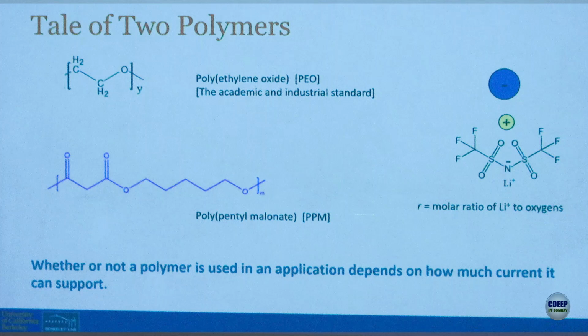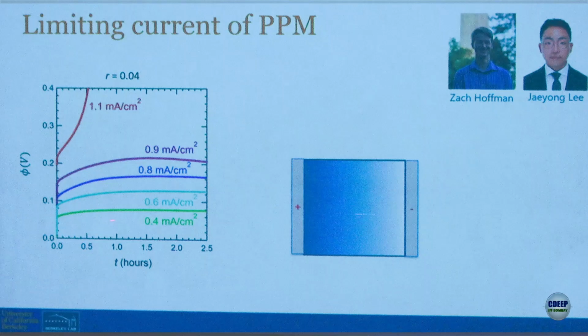And whether or not I can use this polymer in the application depends on how much current it can support. So the question is, how do you measure that current? Well, in this symmetric cell, it's very easy. You apply a current, and the voltage goes up and saturates, and then you see some funny business at 0.9, which you will ignore. And then at 1.1, the voltage goes to infinity.